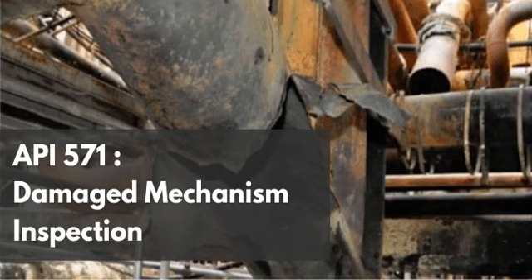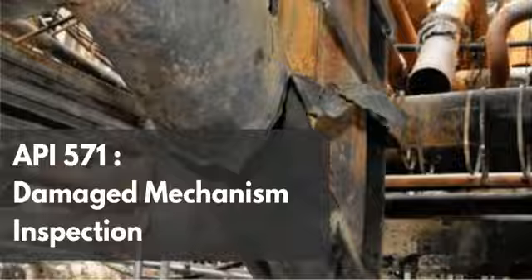But why does it fail, though? Why can't the chromium build its shield? Because building and maintaining a passive oxide layer requires specific chemical conditions, usually an oxidizing environment. A hot, degraded amine system rich in CO₂ is a very different beast. How so? It acts essentially as a reducing environment or a highly aggressive complexing environment where that chromium oxide layer simply cannot stabilize. Oh, I see. As soon as it tries to form, the corrosive soup dissolves it.